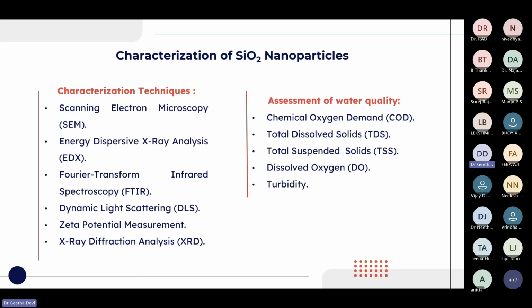The major characterization and analysis are carried out using scanning electron microscopy. Scanning electron microscopy was used to find the surface morphology of the synthesized nanoparticles, and the purity and composition analysis was done using energy dispersive X-ray analysis. Functional groups present on the surface of nanoparticle were identified using Fourier transform infrared spectroscopy, and the average particle size was determined using dynamic light scattering. Surface charge was determined using zeta potential measurement, and also the phase identification was carried out using X-ray diffractometer.